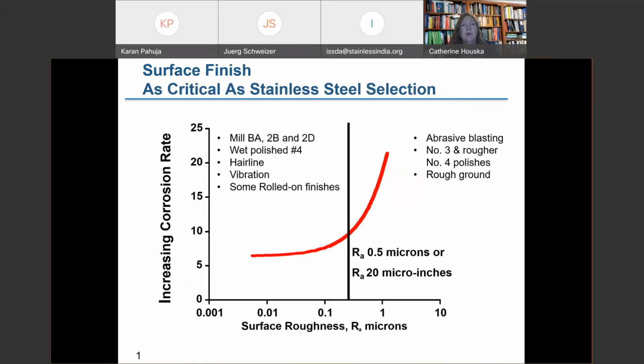I have shown on either side of the line here some of the finishes that typically fall into those that are less than 0.5 microns and those that are greater than 0.5 microns. That's kind of a magic number, because once you are above 0.5 microns, we see a rapid increase in corrosion rate. So if you've got a corrosive environment, whether it is industrial or perhaps an exterior environment where you're going to have salts or pollution exposure, or anything where cleanability or corrosion is an issue, you generally want to stay at a finer finish.